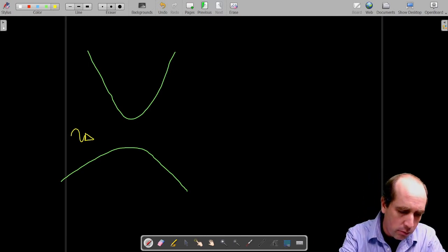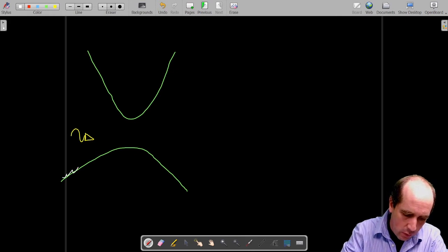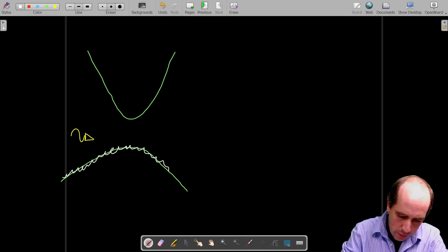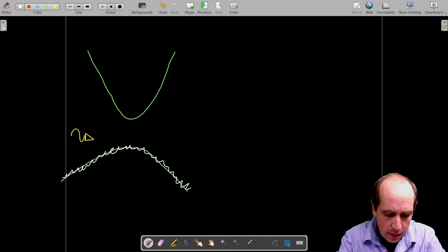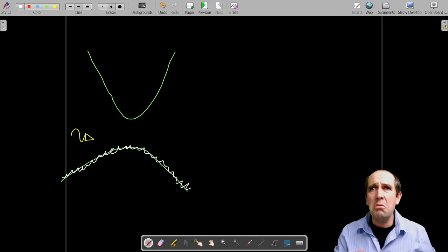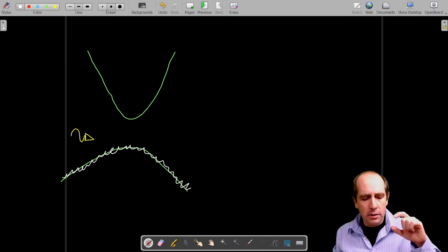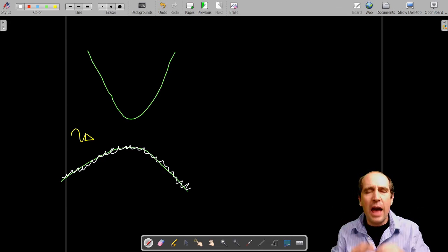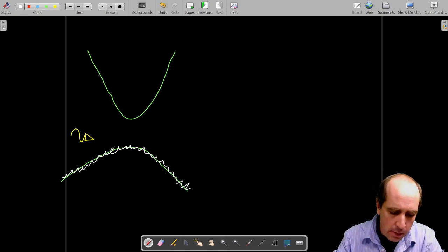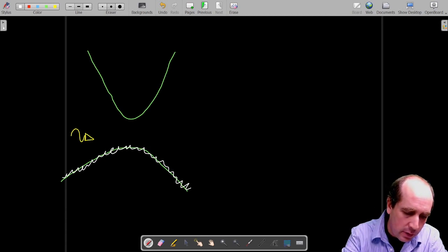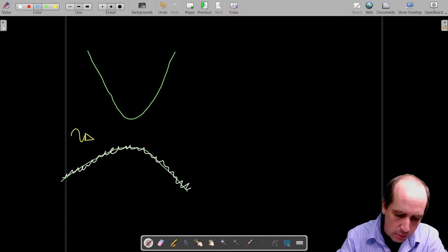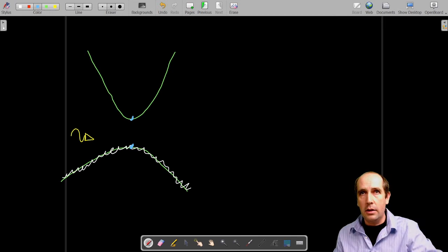There are electrons all over here, so all these states are populated. When the photon arrives, if it has a relatively short wavelength, it has enough energy to produce a transition between the bands. The minimum energy we would definitely need to produce a transition between the bands is for a transition between this top state and this bottom state, between the valence and the conduction band.